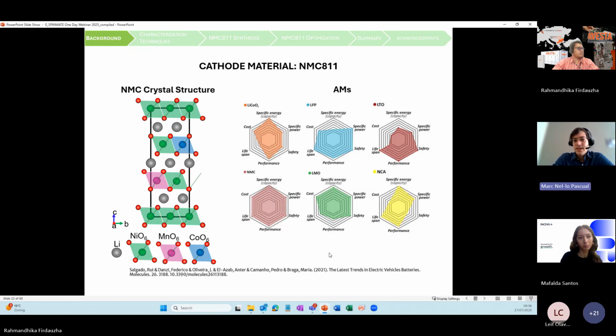Compared to other active materials such as LFP, it shows poorer cycling stability. So in the end, when you're making batteries with NMC, it's because you're looking for increased specific energy, a larger energy density, in this case for a wider range for EVs, for instance. However, one of its drawbacks is that it's a very challenging material to synthesize, and that's why this presentation focuses on how to do this synthesis. Can you go to the next slide?